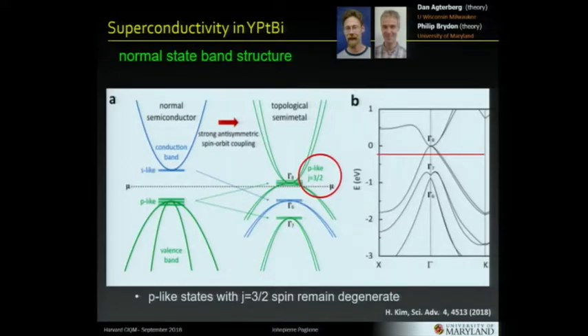So here's a schematic of this band structure, just to explain it a little more clearly. The bands here are made up of the bismuth-based orbitals, the s and p orbitals. And what happens because of the strong spin-orbit coupling, you go from this trivial kind of topology to something like this, where the s-like band actually gets pushed down and the p-like band gets pushed up here, such that you end up with this gamma-8 band near the chemical potential.